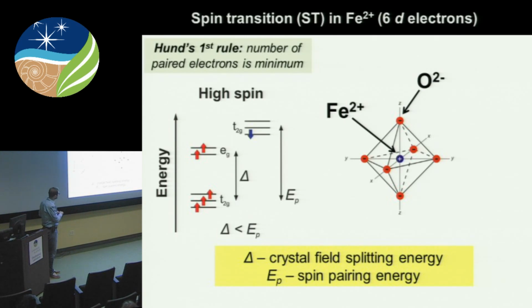Consider an Fe2+ ion sitting in an octahedral oxygen environment. The electrostatic repulsion of oxygen p electrons on the d electrons of iron will be such that the d electrons will split into two energy levels, the T2g and Eg levels. The energy difference between the two levels is termed crystal field splitting energy, or simply delta. Hund's first rule governs the distribution of electrons among these orbitals, such that you end up having 5 electrons with a spin-up orientation, and then the 6th electron with a spin-down orientation here.